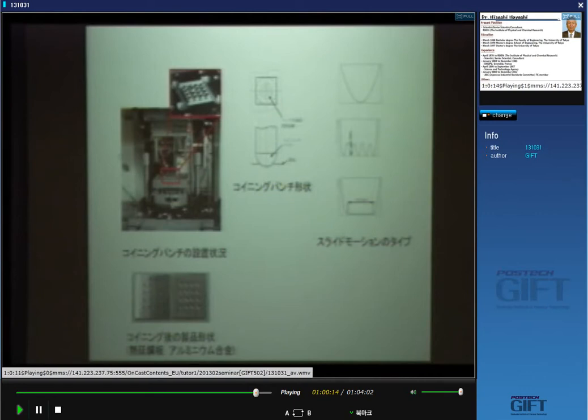And they measured the spring back behavior like this. This is just after the forming, and after removing the punch, the change of this valley, and they define the spring back ratio like this. And in the other case, the transfer of the shape of the punch into the metals, they also define the shape transfer ratio like this. So the coining mode, coining slide motion is very effective. And we want to apply the control or suppression of spring back of high strength steel sheets.